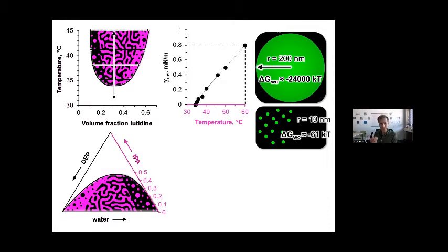Just now, instead of the temperature as the indicator for what interfacial tension we have, the solvent fraction going here from 0 to 50%. I'm now plotting the interfacial tension against the solvent fraction. And as we quench the system from the miscible region to the immiscible region, we decrease the solvent fraction from 50% to 0, going from right to left here.